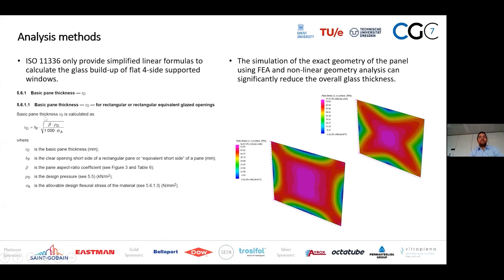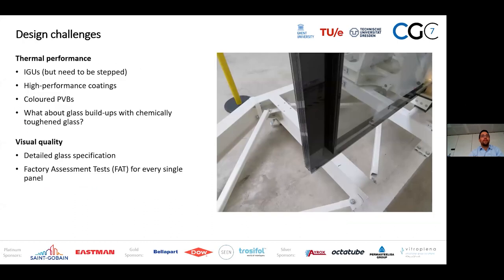Obviously, the aim, as you can imagine, in order to optimize the performance of the vessel, is to reduce the weight. ISO 11336 only provides some simplified formulas for flat, four-side supported panels. Most of the yards are using these equations these days, but if we want to achieve actual optimization of the glass weight, we need to use FEA and nonlinear geometry analysis to take into account the exact shape and geometry of the panel, and also the membrane action that is developed in its deformed condition. Keep in mind that we are talking about 100 kPa loads in some locations, so membrane action will be activated.